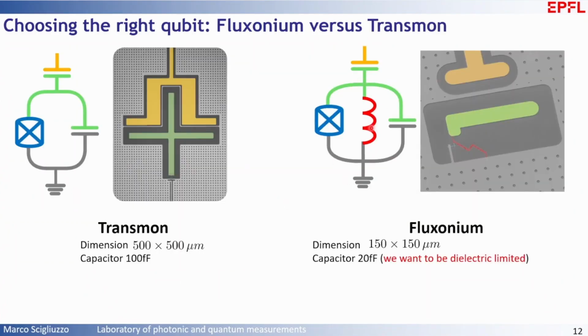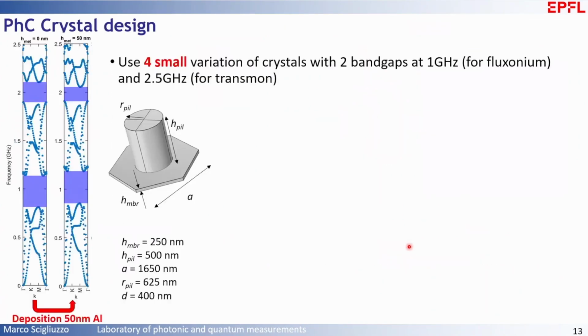We switched to fluxonium. So now we still want to be dielectric limited, so we still want to have a relatively large capacitance for the fluxonium, but this should still allow much smaller dimensions of the suspended structure. An additional point is that going through the fluxonium, we can reduce the operating point without needing huge capacitance. So we can shoot for a frequency of the qubit around 1 gigahertz.